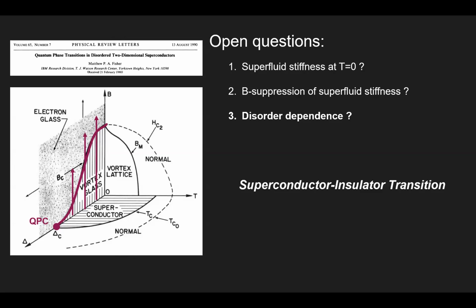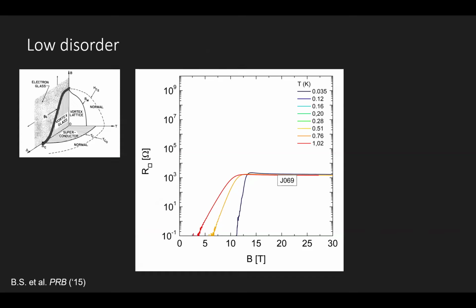This is the whole story in the field of disordered superconductors. If you apply a perpendicular magnetic field to a disordered film, here is a set of magnetoresistance curves, resistance versus magnetic field at various temperatures, for the same film. You see that the resistance is quite large, of the order of kilo-ohms, and what you see is a relatively straightforward and standard transition to the normal state. And the evolution of the curves follows what we expect for thermally assisted flux flow and all this activated behavior of vortices. So this would correspond to a film which is, say, at very moderate disorder.